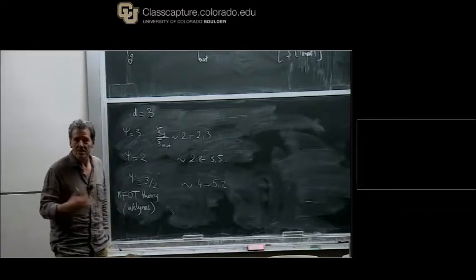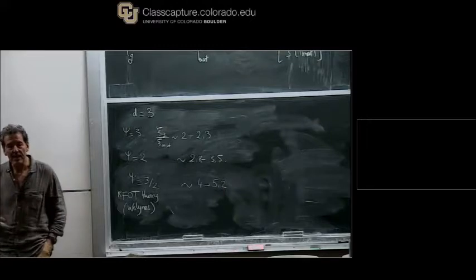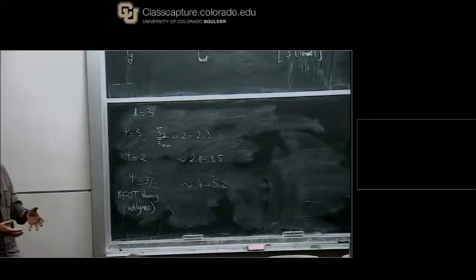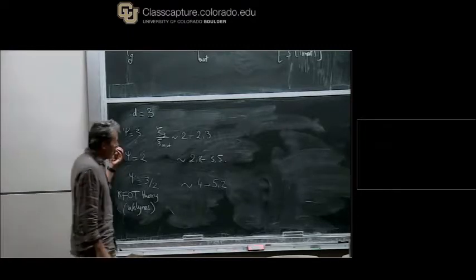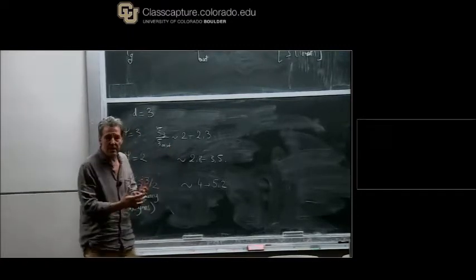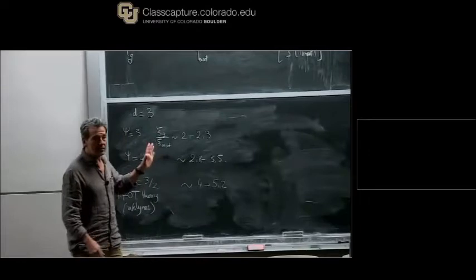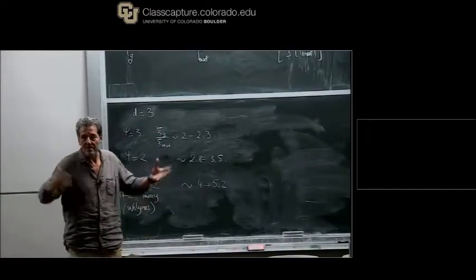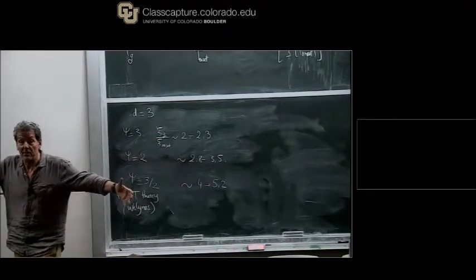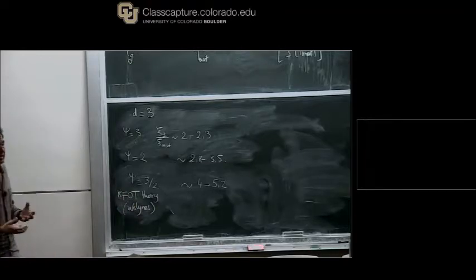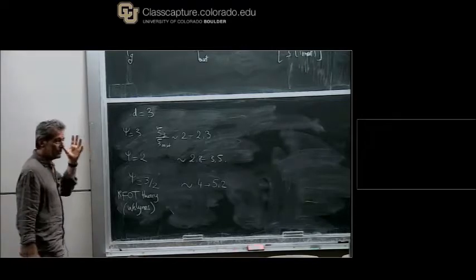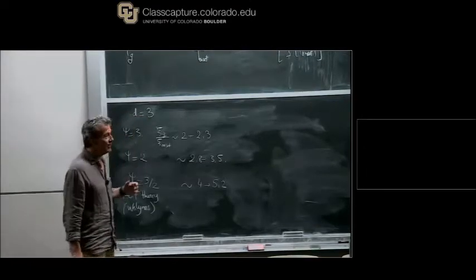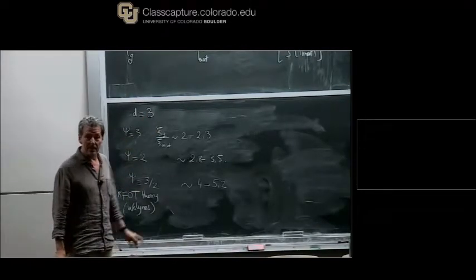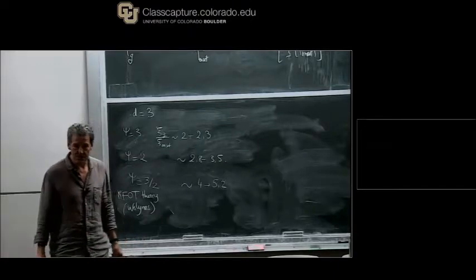Okay, so you can say something about coarse graining, scaling, and you can check your asymptotic predictions. Here, basically, that means that whatever you want, you will never be in a region where you can check your asymptotic predictions, where the length scale is supposed to be very, very, very large. Okay? And this is an intrinsic consequence of the fact that we presumably have activated dynamic scaling in the glass transition problem.